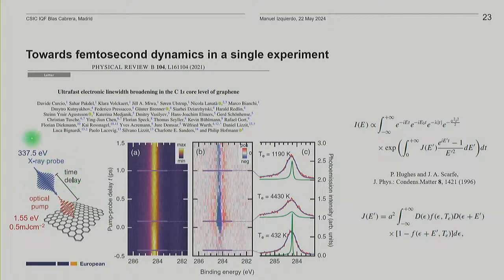And then they probed the material with 337 electron volts. So basically, this is the core level, the carbon 1s core level as a function of time, and these are the different scans. And what you can see is a huge increase in line width of the core level. Basically what they did is they analyzed the profile of the core level by starting with this expression of the XPS intensity proposed by Hughes and Scarfe in 1996, where this part takes into account some electron hole interactions and things like this.